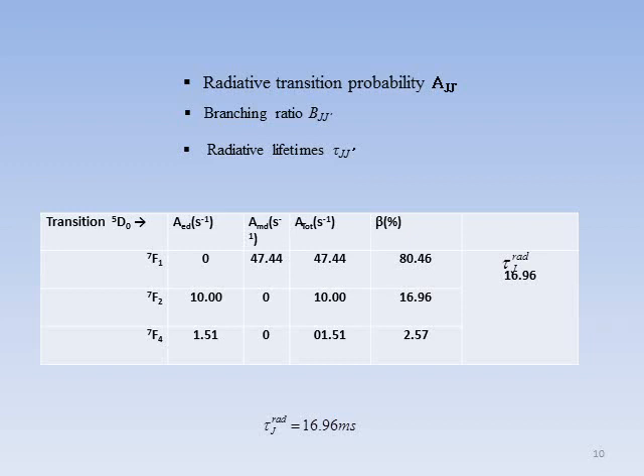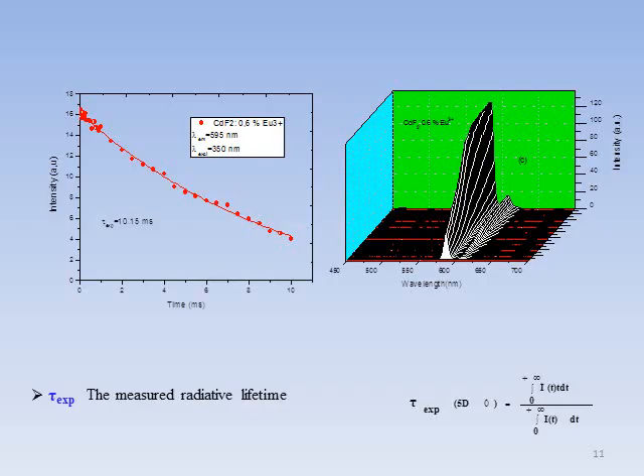The other spectroscopic parameters of interest were also investigated. We found the radiative transition probability, the branching ratio, and the radiative lifetime, as depicted in these tables. For the decay time and quantum efficiency, we recorded the room temperature time resolved emission spectra of CdF2 with different concentrations of europium, recorded in the spectral range of 450 to 700 nanometers and excited with 350 nanometers wavelength. We considered it correct to represent only one time resolved spectrum among the three concentrations studied.